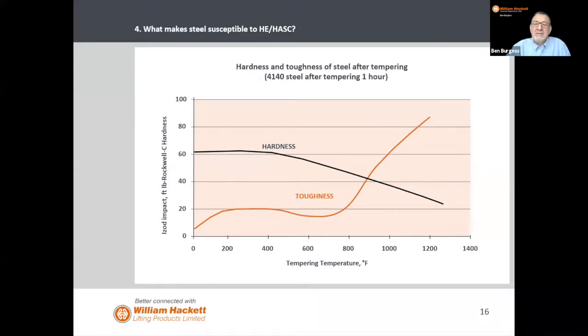The manufacturing process that we believe should be followed takes you through a higher temperature and for a greater length of time so that the toughness and hardness are combined. Now, as a manufacturing process, that obviously takes longer, requires more energy, and therefore makes the product more expensive, but it makes it suitable for the environment that we're talking about and the applications that we're discussing. Now, for every grade of steel, raw material that you're talking about, if you put it through the same process, you'll get a slightly different product attributed to it. So the consistency of the raw material and the manufacturing process must be aligned.